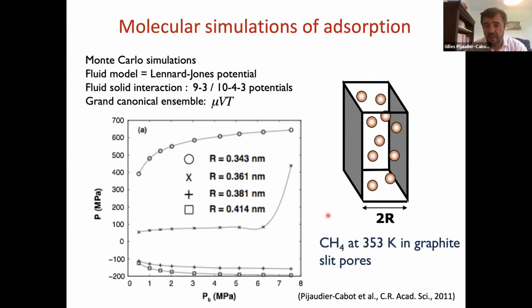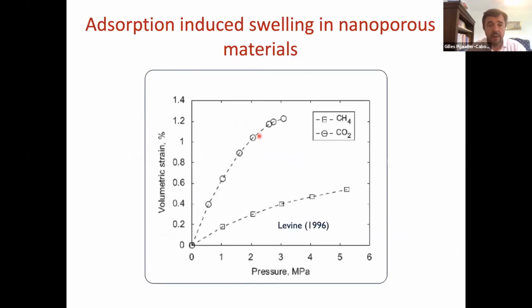In fact, what you obtain in the case of a slit pore, with spacing in between the pores, you get enormous fluid pressures inside those micropores. What's most important is that depending on the opening, the width of the pore, you get a very different pressure. Going back here, you'd see that deformation can amount to, let's say, 1%.